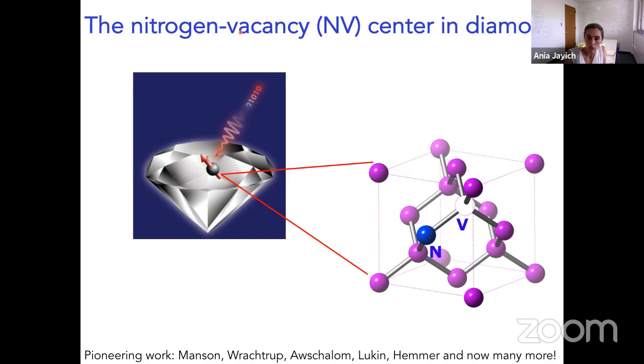So the NV center, as shown here, is a localized defect in the diamond lattice, specifically a nitrogen substitution and a nearby vacancy that interrupts this periodic repetition of carbon atoms, shown here in purple. And so this artificial atom lives in a diamond lattice rather than in a vacuum.